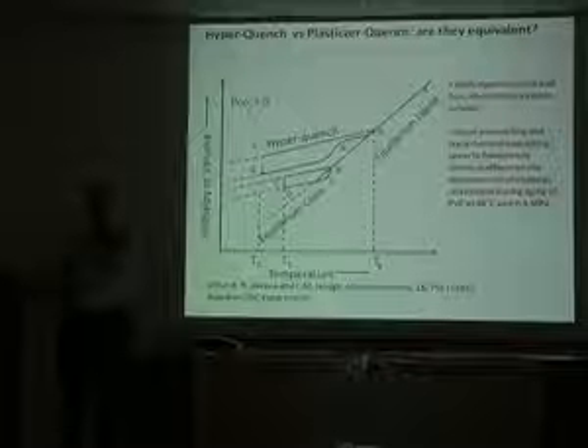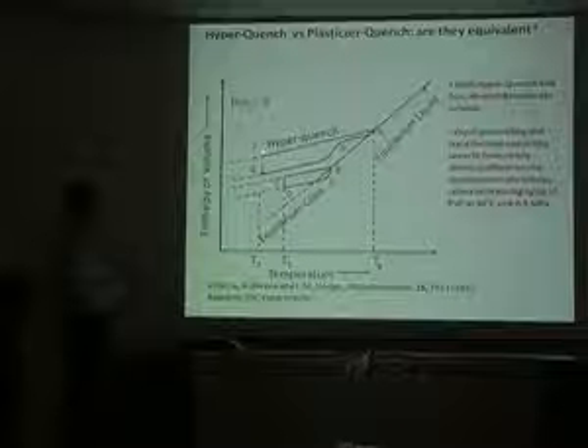And the reason we were interested in this was not only what we had seen, but there's been some work by Berens and Hodge where they actually took particles of polyvinyl chloride polymer, and they would expose them to a vapor and then jump the vapor, and then they would do enthalpy recovery experiments. Okay, and this was the kind of graph they made, which I'm not sure I totally agree with, but this was what they said was happening when you hyperquench a glass. It comes down, it recovers quickly, and then when you heat it, it does something funny like that, where this is the normal glass, where you heat it, and then you come up and you get this overshoot, and that's the enthalpy overshoot.